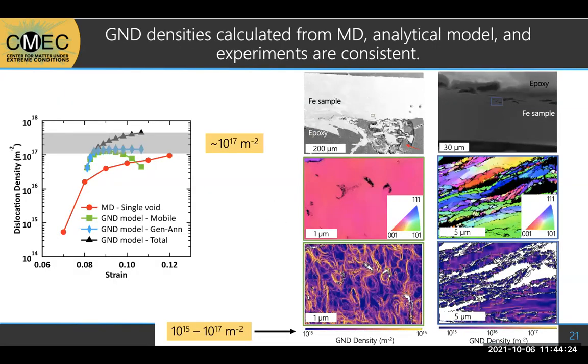Okay, so this is actually a really cool result, at least I think. The graph on the left is exactly what I just showed, but on the right are more EBSD maps, and then the bottom two are dislocation density maps that I was able to calculate from that same MATLAB toolbox that I used earlier. And so it's really cool to see that the numbers, 10^17 for the models and 10^15 to 10^17 for the experiments, are only an order of magnitude off or so.